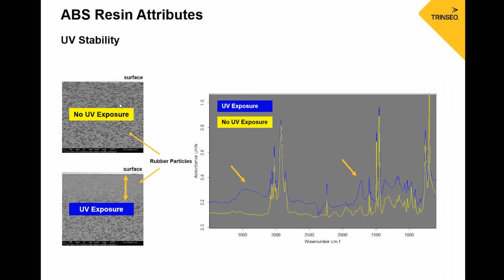The top of this image represents close to the surface. This is a cross section of the sample. On the top, you can see it's consistent from bottom to top of that cross section. In the sample that was exposed to UV energy, you can see near the surface, it looks like that rubber is disappearing because you're not seeing it in this image. It's actually still there. It's not disappearing, but those double bonds that the stain attaches to allow us to see that rubber are going away because of cross-linking of the rubber. So that's going to become more brittle with additional cross-linking at the surface from that UV degradation.